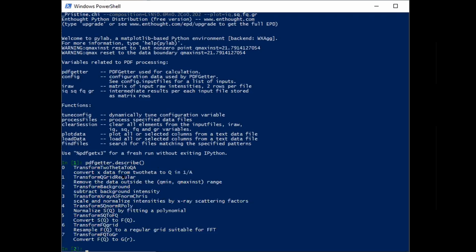And then it will transform to the grid regular. And this is basically defining the data range. One thing is to fit a polynomial to mimic the background. So I talked about that. You have the background, right? You have, let's say, the Compton scattering, which sometimes cannot be strictly measured. Then you have the absorption issue, optimization issue, that is actually adjusting your intensity, right? So all those things are dealt with in PDFgetx3 by a polynomial fitting.